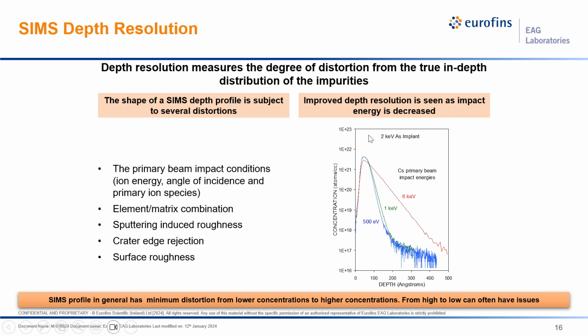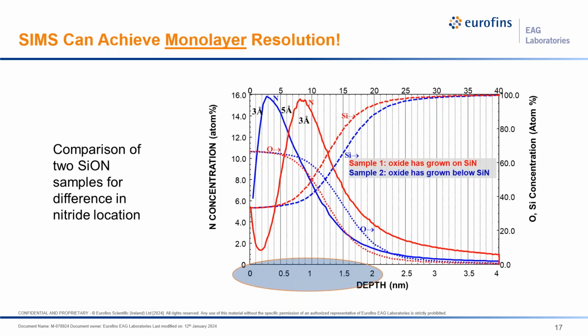There are other sputtering considerations, such as the combination of element and matrix, some sputter-induced roughening effects, as well as crater edge effects that can also compromise depth resolution. But either way, we can tune this and try to get the best depth resolution for very thin films. In particular, we can measure thin films down to the angstrom level.